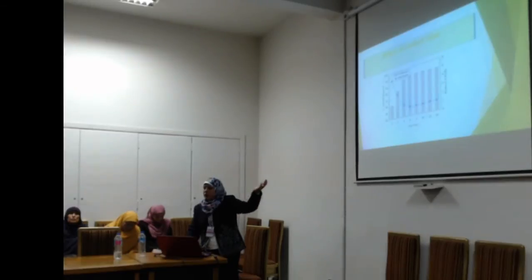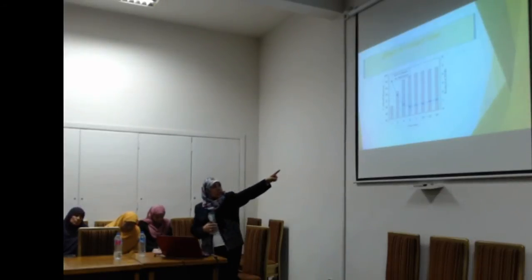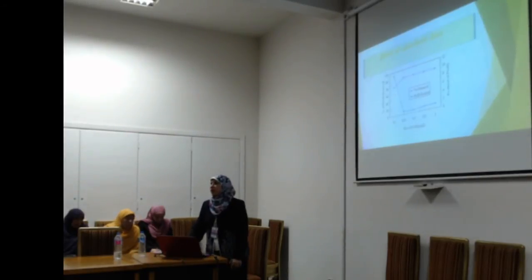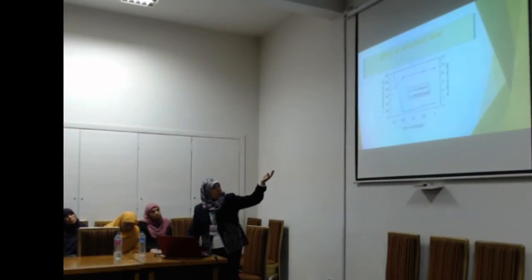The effect of contact time was very short, where it was constant at 5 minutes. Then, since the adsorption process is related to the surface area, we studied the adsorbent dose. For nanohydroxyapatite, we used doses from 0.1 gram to 1 gram.